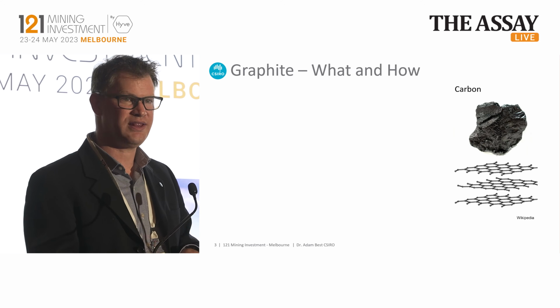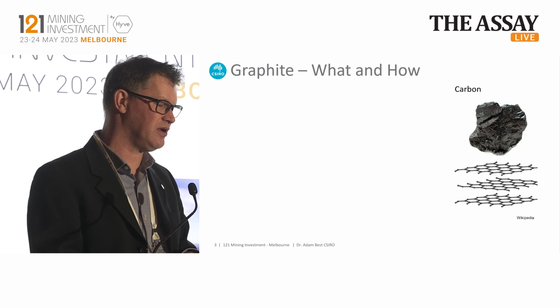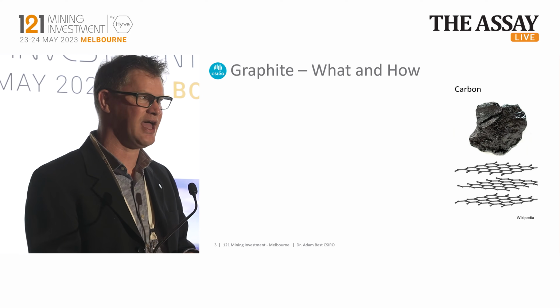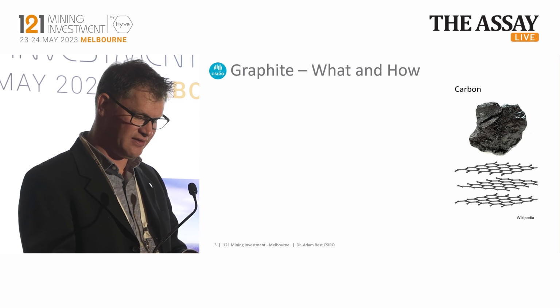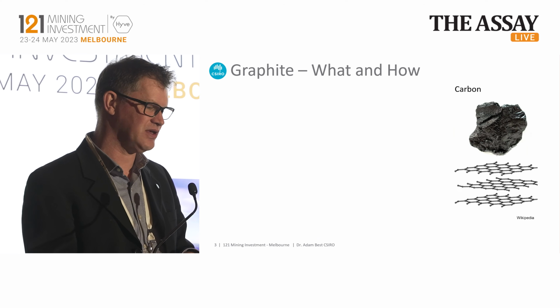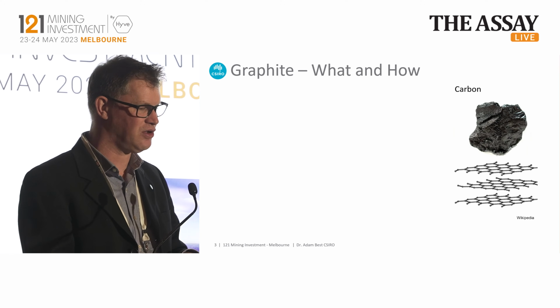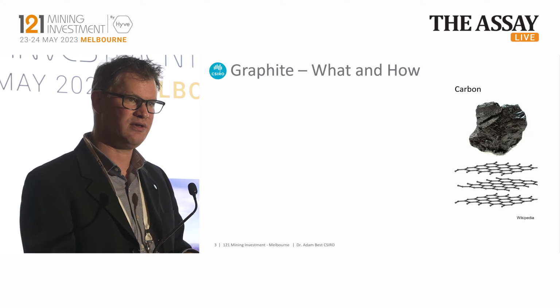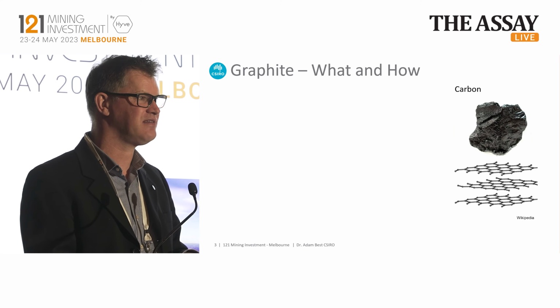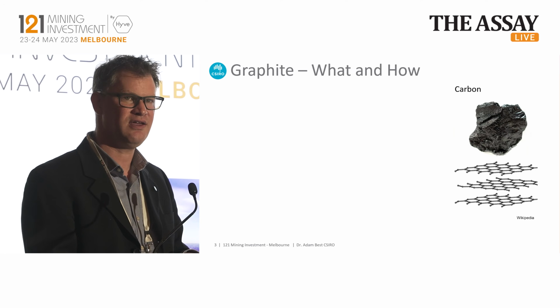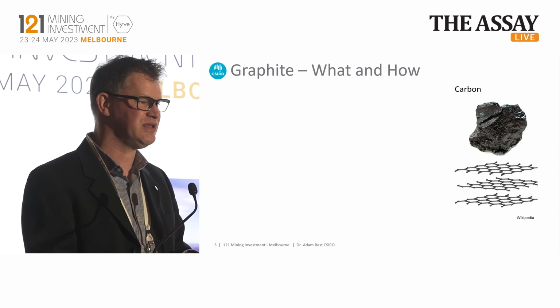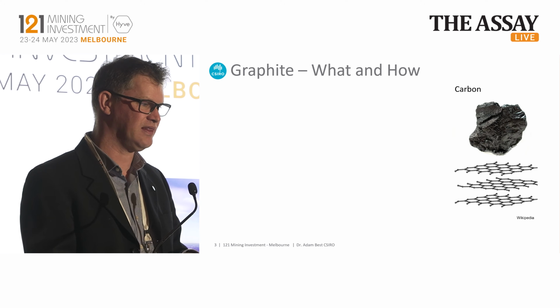So graphite, the what and the how. Why are we interested in graphite? Well, graphite comes from carbon. It's a layered material, and those interstitial layers that you see there on the image on the right-hand side underneath that carbon block is where lithium is stored. It's that interlayer spacing which is the real criticality that's required. The more graphitic a material is, the more lithium that we can store in there.